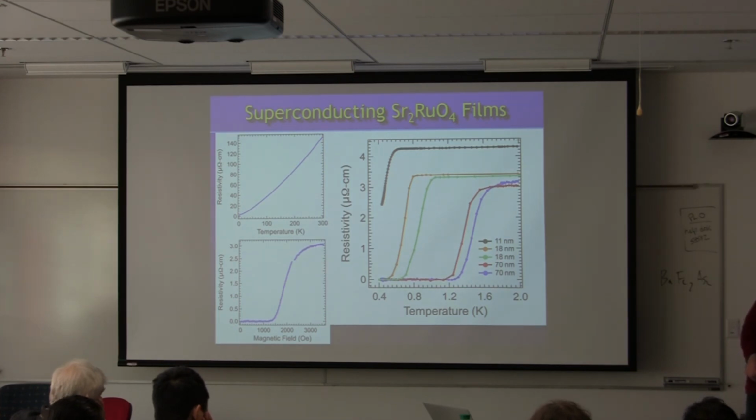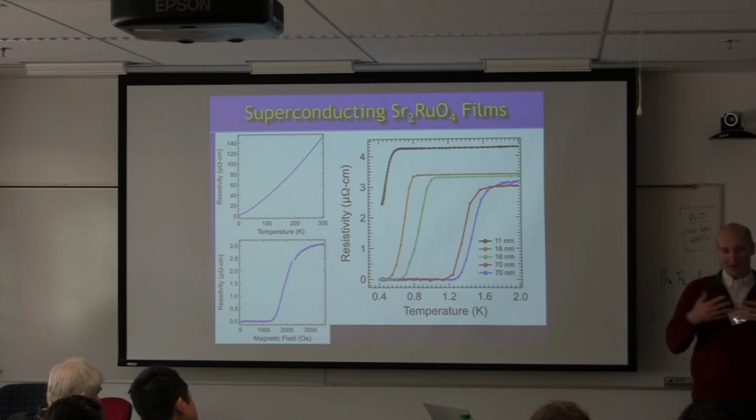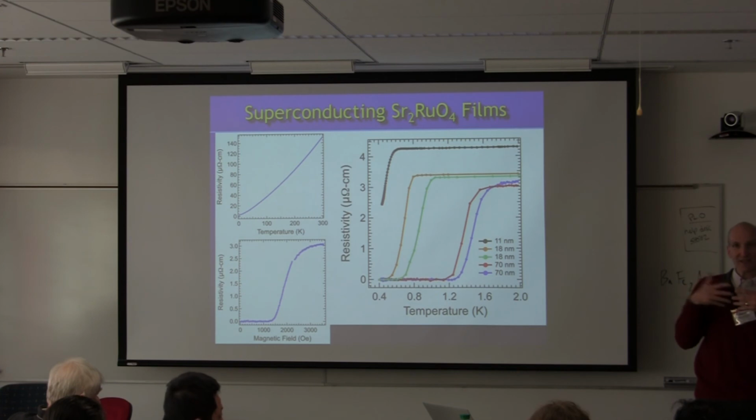So is there some other factor that's not being considered then? My question about impurity scattering? No, I would say it was the opposite. In single crystals, you need to be very concerned about the purity of the material, as we do in films. A few hundred parts per million of impurities can destroy superconductivity. We made films 20 years ago that had less than 100 ppm of impurities, and they were not superconducting. The disorder was not from impurities, but rather from out-of-phase boundaries in the films. We could see those by TEM. So we had other defects, and that's what I think is really limiting here.